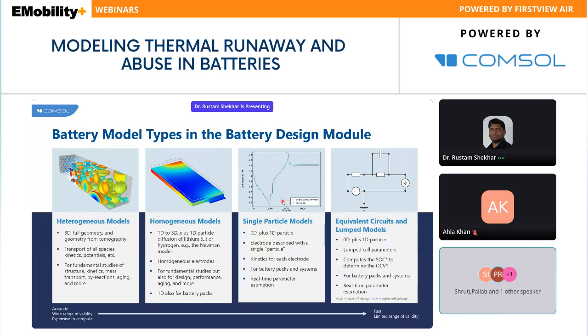And there is one more approach with a single particle. If you are not working at very high C rate conditions where mass transport is the limiting rate, then you can just work with single particle models and see the detailed electrochemical phenomena, to see how gas will form in the electrode, how lithium plating will happen. So this scenario can be accommodated by using a single particle model. The single particle models generally are 0D models, so they won't involve any kind of geometry. When geometry is not involved, that means this model will be very fast to solve. So then you can create a battery pack, or you can use it for real-time parameter estimation, or in onboard applications. The single particle models can be used to see how the cell is performing, and based on that, if you figure out any failure mechanisms like overcharging, discharging, and uneven temperature rise, then single particle models can be deployed.